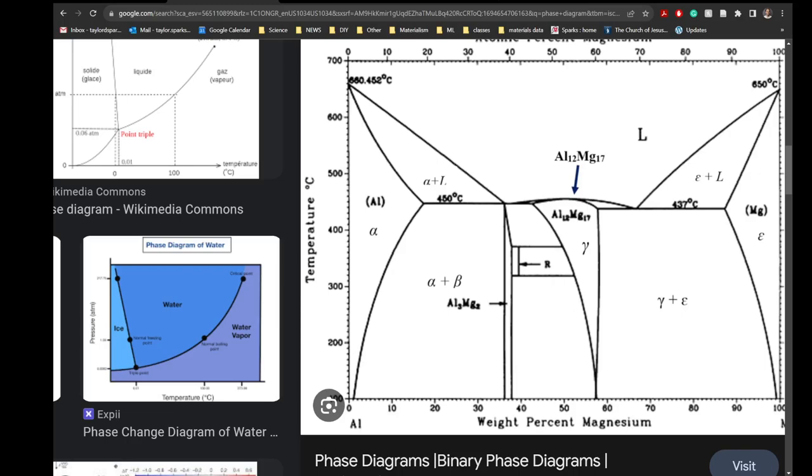Why does this matter? Let's say I'm trying to mix this up in the lab and I want to make a compound with R, and it's got to be completely phase pure, 100% R. That's hard to make, because you've got to hit it right on the head. If you weigh things out wrong, or something volatilized in your furnace and you lost one of your components, which happens all the time, especially with volatile light elements like lithium or sodium that float off in your furnace, then even though you aim for this composition, you're actually here, which means you've got two different phases, which is a bummer. So you have to remake it, adding a little bit of excess, because you know that some of it's going to volatilize off. It's just hard.